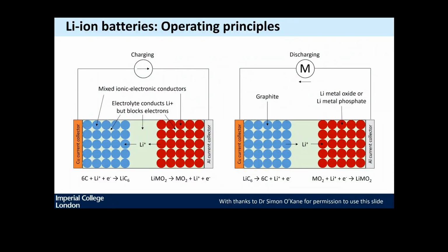I'm just assuming that there is this extra dimension, radius r, through which things diffuse, because this is going to allow me to make the difference between an electrode that has lots of Li0 at the surface and so can deliver a lot of power because a lot of reactions can occur at the same time, and the electrode that doesn't have a lot of Li0 at the surface may still have them, but they are deep inside and they take a while to come to the surface.